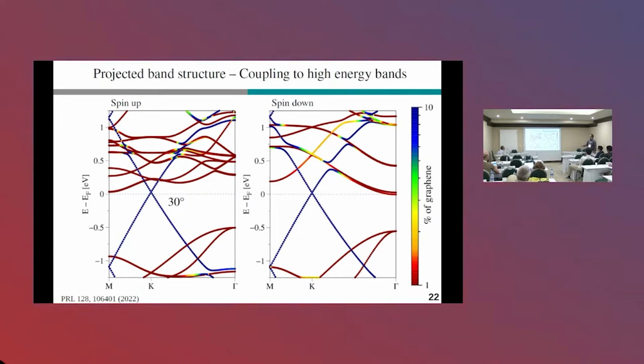And in fact, for the spin up case, you will find no coupling to these low energy substrate bands, while there is quite a weak coupling to these high energy levels. In contrast, in the spin-down manifold, you find quite a strong coupling of the Dirac states to these high energy levels. And this is what pushes the spin-down Dirac state to lower energies for this case.